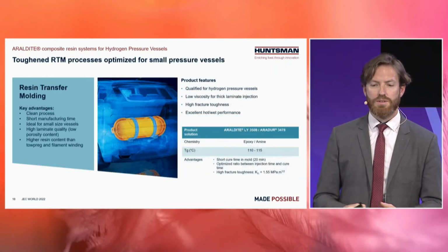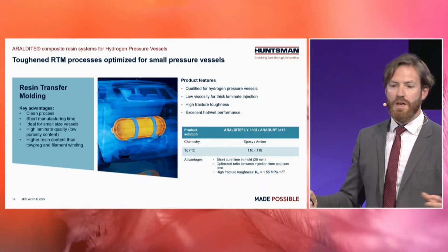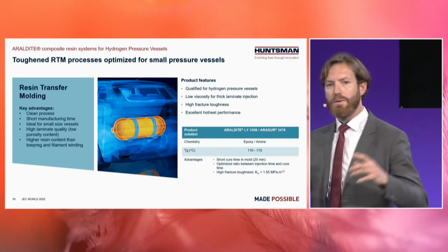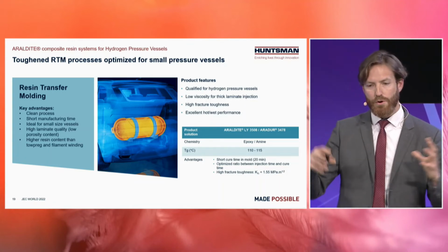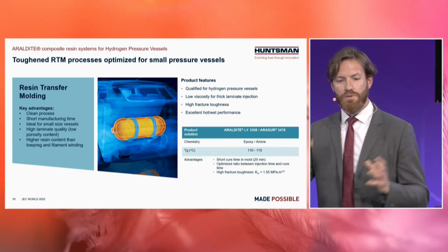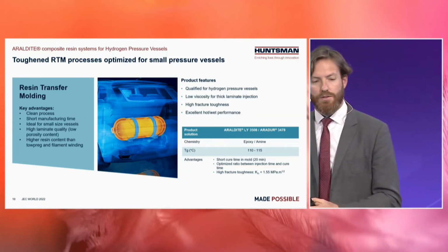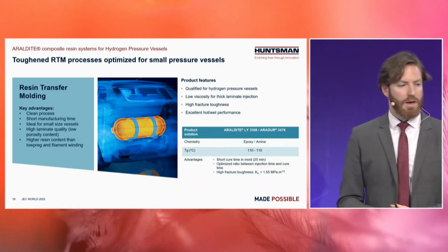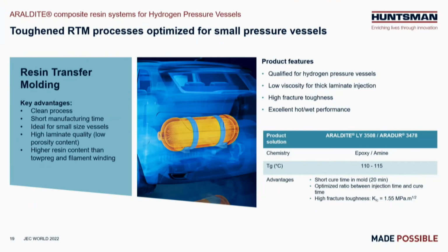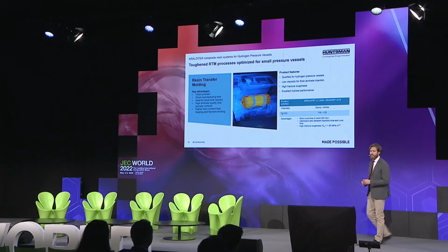The second type of process is resin transfer molding. How does it work? You have a liner, you braid or make a dry preform around your liner, and then you put this into a tool, you inject under pressure, and you demold, and you have your part ready to go. The advantage is that it's a clean process. You can reduce the manufacturing times. The in-mold cure time can be quite low, 20 to 30 minutes. And the epoxy resin that we have developed specifically for this application has a high fracture toughness for excellent dynamic properties, so cycling test compatibility and so on.